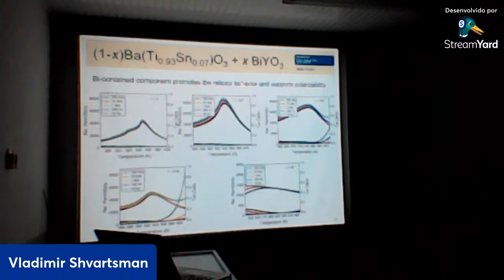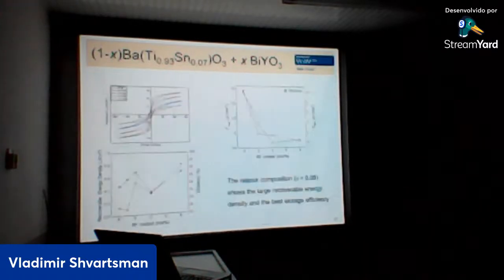Therefore, we introduce bismuth to also increase our dipole moment. So this is the change in behavior with the composition with more bismuth yttrium oxide. You see, we start from classical ferroelectric behavior for barium titanate. Then our peak becomes broader and broader. Finally, it becomes strongly broad and also strongly frequency dependent. So we have a transition to relaxor behavior.